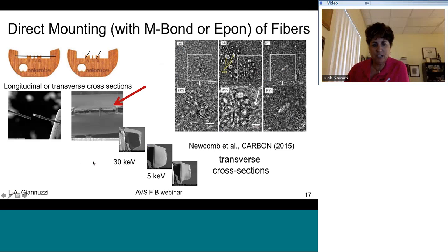This is something I did with a graduate student at Georgia Tech a few years back. I was looking at carbon nanotube embedded carbon fibers. And first we did a longitudinal section by just gluing these fibers to these half grids. If you do this, the one thing that you definitely want to do before you FIB-SEM the sample is to FIB cut the sample through. And this will release any stress in these fibers.